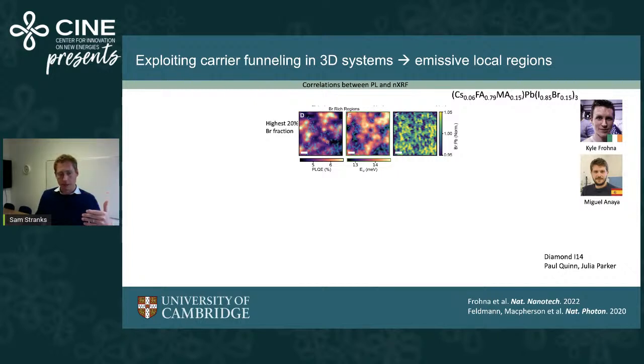I'm showing optical maps from these samples. So this is looking at the local photoluminescence quantum efficiency in the color scale here, and also the Urbach energy of these materials. This gives us an idea of the degree of disorder in the band edge states. A lower Urbach energy is better and has lower disorder.